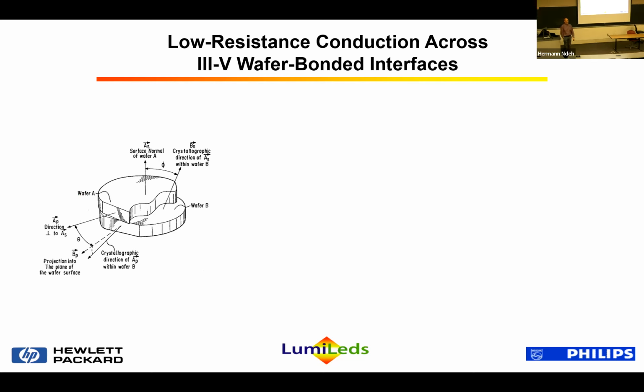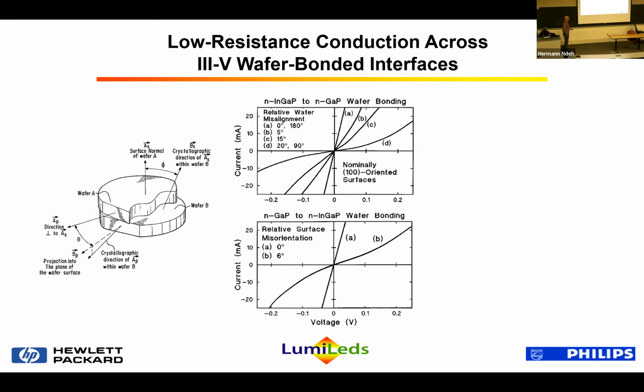And one of the things that we realized in developing this technology is that to get good electrical conduction across the interface when we fuse the wafers together, it was very important, even though the materials were lattice mismatched, to align the surface orientation and the rotational alignment of the crystal. That wasn't something that was obvious to us when we were doing the work. So this is a schematic of 2 different wafers being bonded together with 2 different surface orientations and 2 different rotational alignments. And what we found, and this was true of every material that we tried to bond, in this case, we looked at N-type indium gallium phosphide to gallium phosphide, was that as we changed the relative misalignment rotationally, we basically could introduce a hetero barrier at that interface.